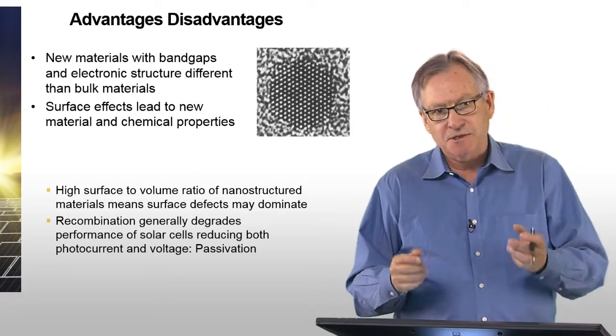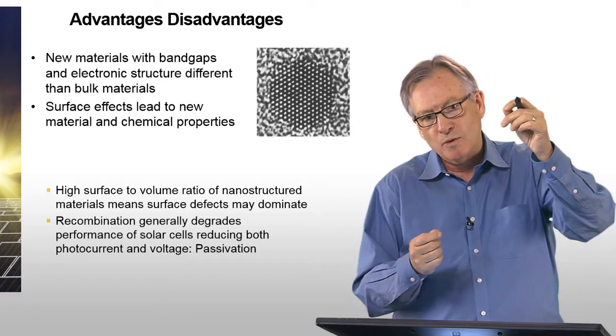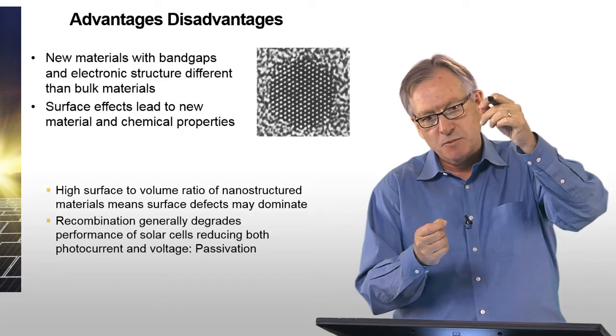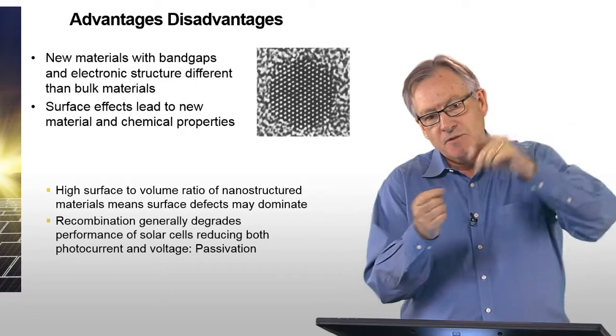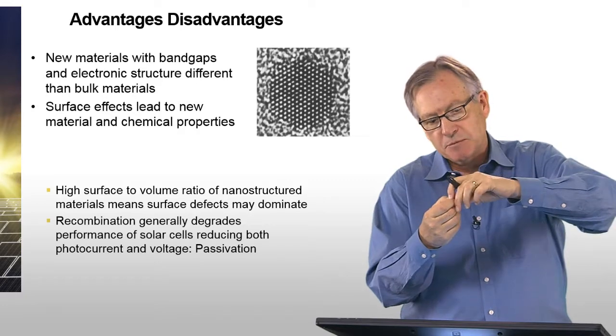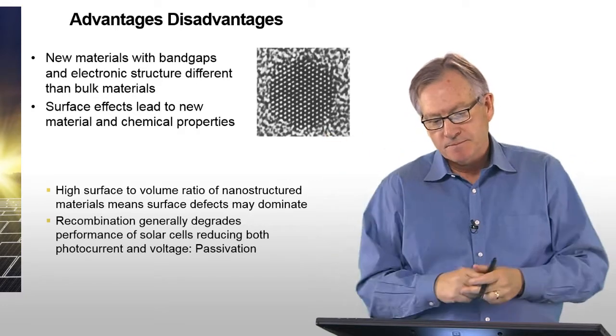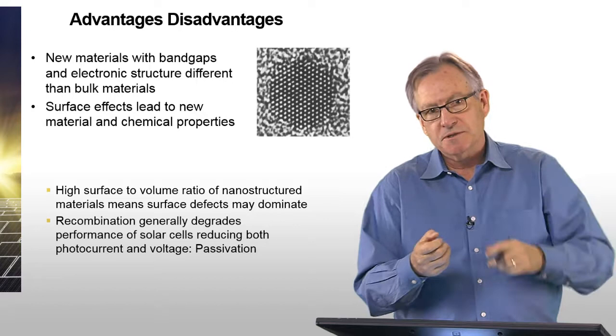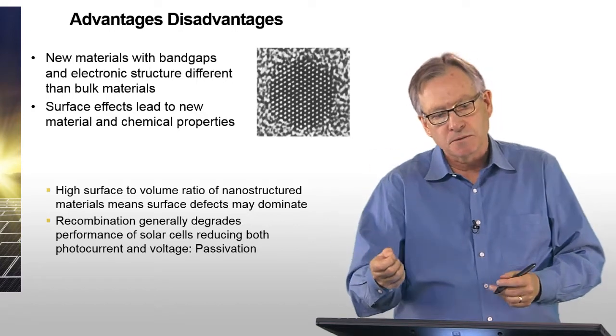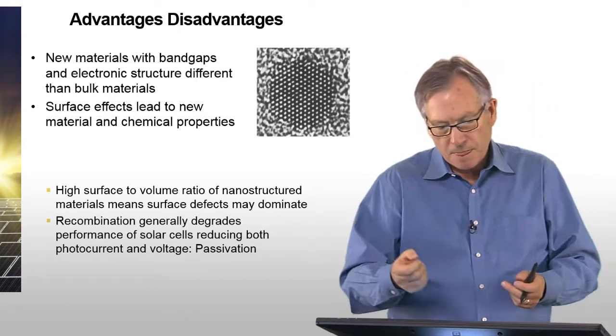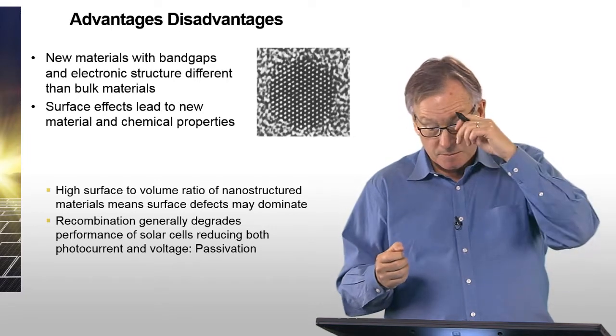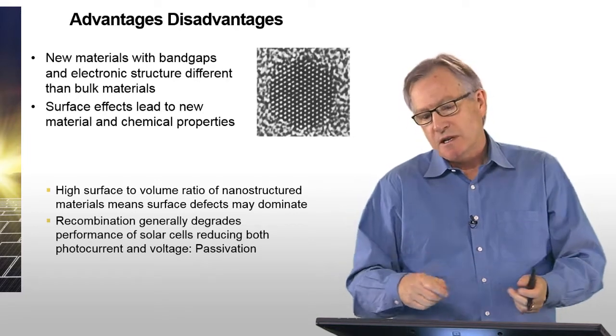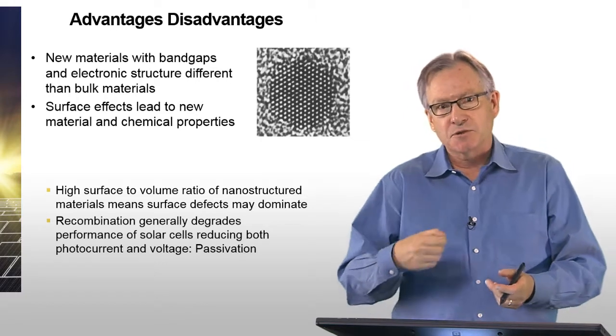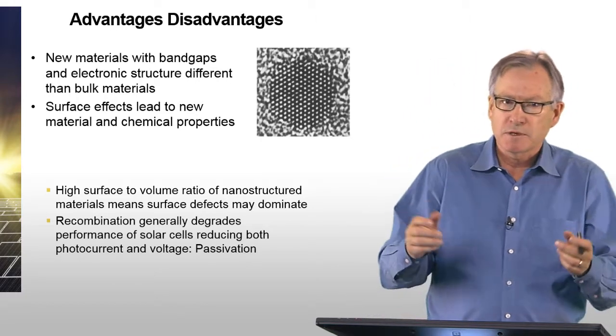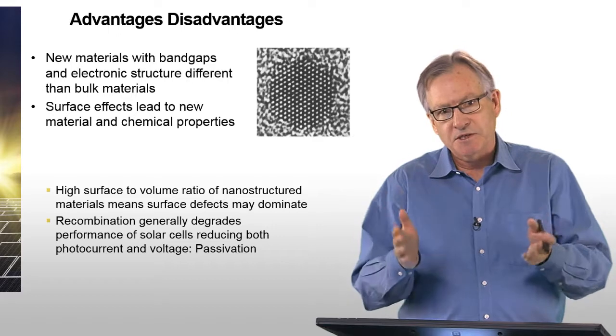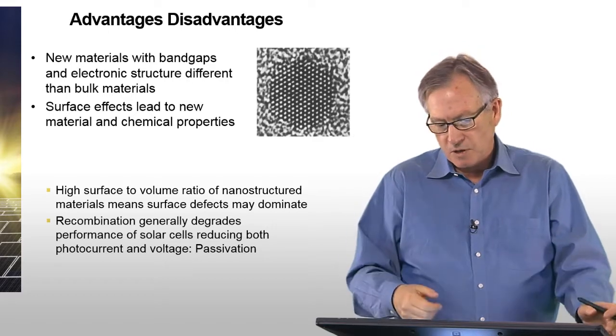And recombination is the process in which an electron and hole that have been created by light, instead of moving apart and being collected, fall back down and basically recombine, either giving off light or heat. So anytime a particle recombines, it basically means you've lost it to photocurrent. And since you've lost it, that reduces the efficiency. It also increases the dark current, and as you increase the dark current, recombination then degrades the voltage, and so it has two negative effects.